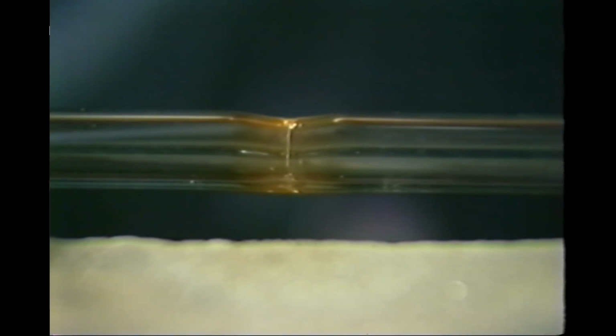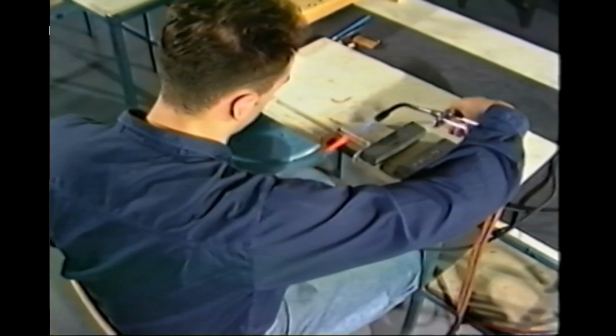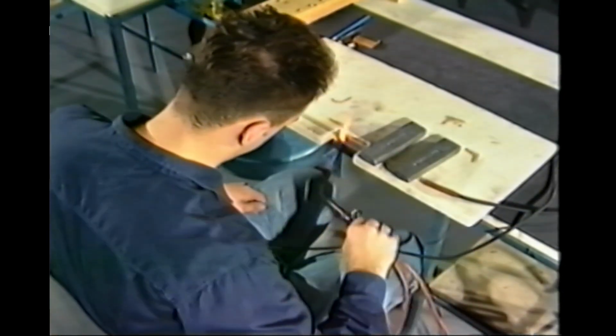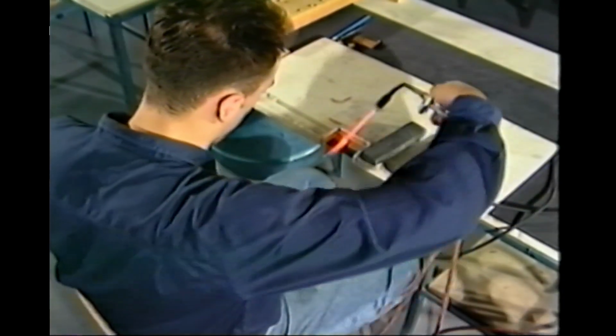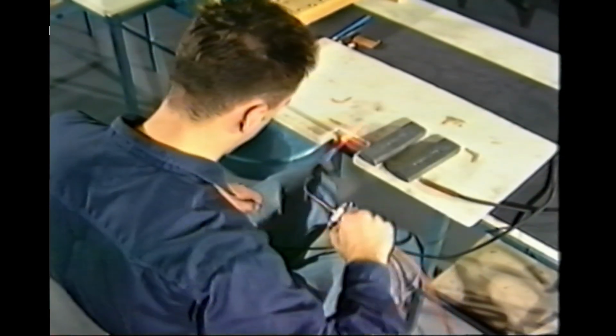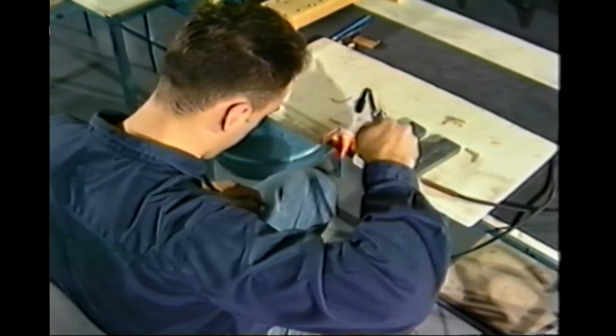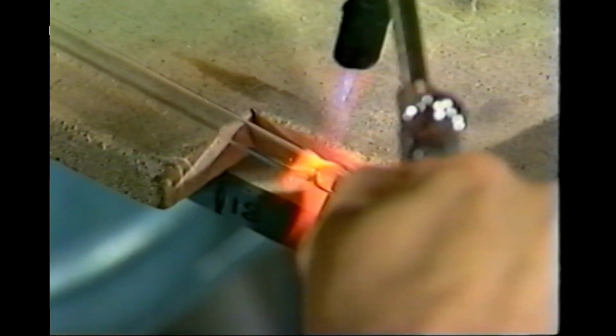If this is not counteracted with an extra melt before blowing into the tube to restore diameter at the melt point, an uneven joint will result. At the end of the first full melt, when the glass at the joint area reaches a bright red heat, cease flame rotation. Bring the flame to play on the top of the melt area and heat this collapsed area slightly longer without increasing the depth of the collapsed glass.